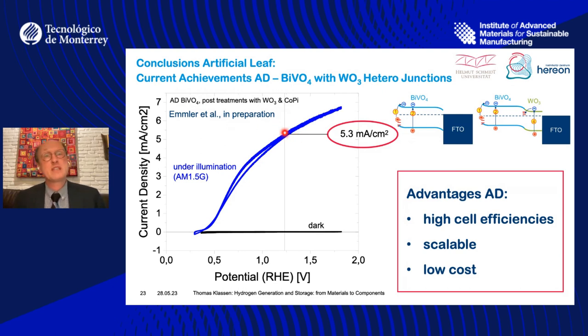So this is a tandem cell, so to speak, and it helps to draw the electrons by bending towards tungsten oxide. So in this way, we were able to achieve a rather high photocurrent, which is, I think, better than pure photovoltaics and separate electrolyzers. So the technology basically gives you a high cell efficiency, and it's scalable, and the deposition method is also a low-cost method.